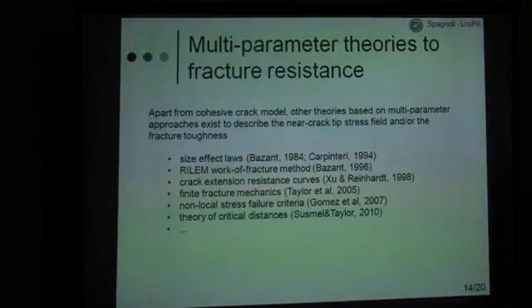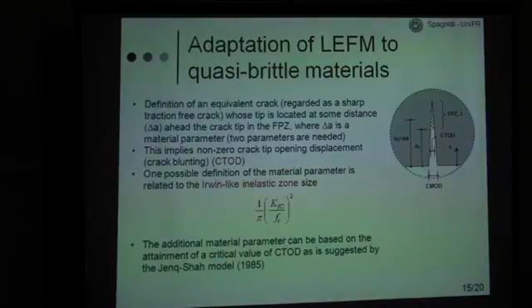All of them make use of some additional parameters for giving the fracture resistance of the material. When you use linear elastic fracture mechanics, you have to adapt the theory to add some additional parameter. So, if you consider the fracture process zone, one way to deal with this adaptation is to consider some distance, delta A, which is extending the traction-free crack length into the fracture process zone. This, of course, implies that you have some non-zero crack tip opening displacement.